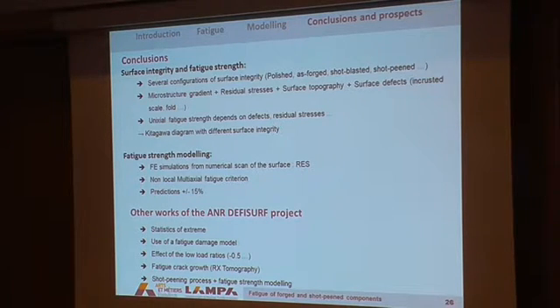So to conclude, I just want to sum up my talk by saying that we studied several configurations of surface integrity, including the effect of microstructure gradient, residual stresses, surface topography, and the presence of defects. We performed some plane bending tests, and by using finite element simulation and a simple non-local multiaxial fatigue criterion, we were able to predict the fatigue strength, taking into account the effect of the residual stresses, with an error bound of plus or minus 15%.